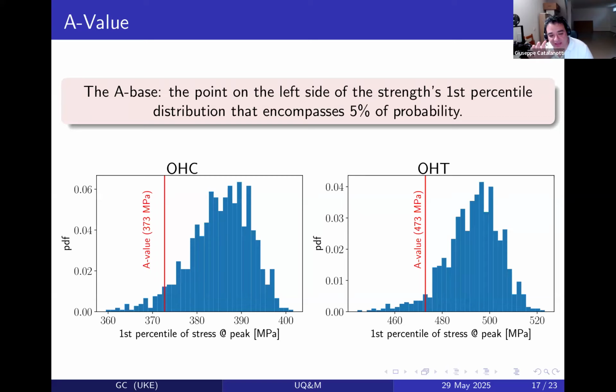So if you have a strength, what they will usually tell you in the aeronautic industry is give me the B value or the A value. The A value is for critical structure. In this particular case, it's extremely simple, because I know the distribution of my parameters. I can estimate the first percentile, get the distribution of the first percentile, and after determining the 5% probability on the left, I get the A value. And the A value is there for OHC and OHT.